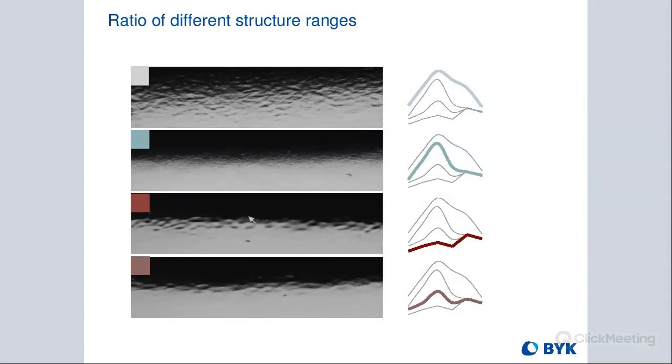And that gave it a more brilliant look, better wet look. But also because the shortwave was brought down a little too much, that revealed the orange peel on the surface. And so the top coat application was then optimized to actually provide a little more shortwave structures so that it better balanced the long wave structures and gave it a better overall look.